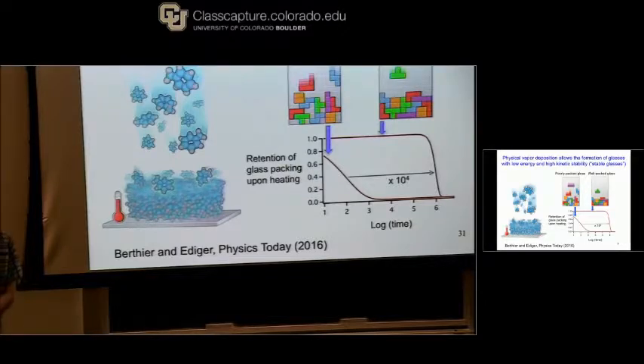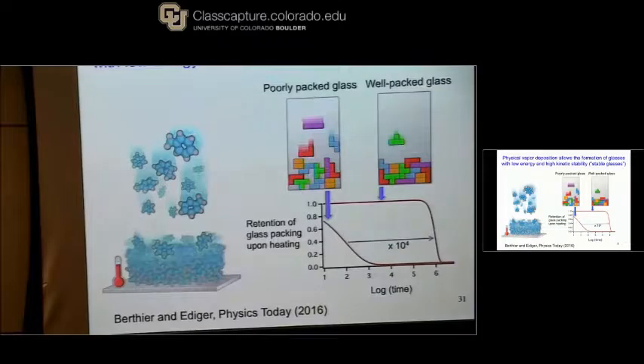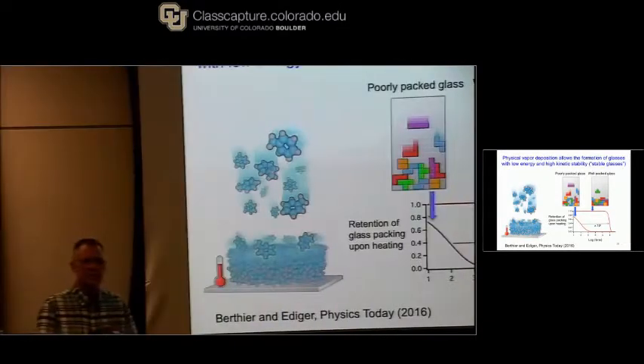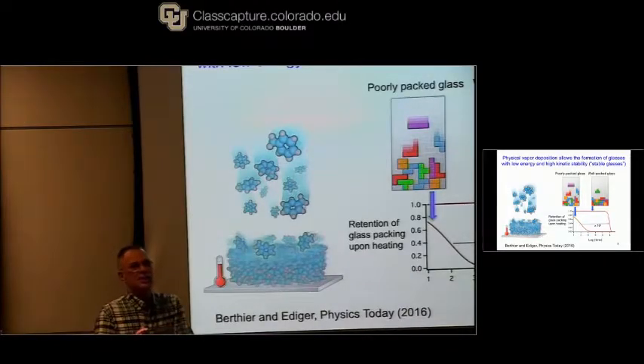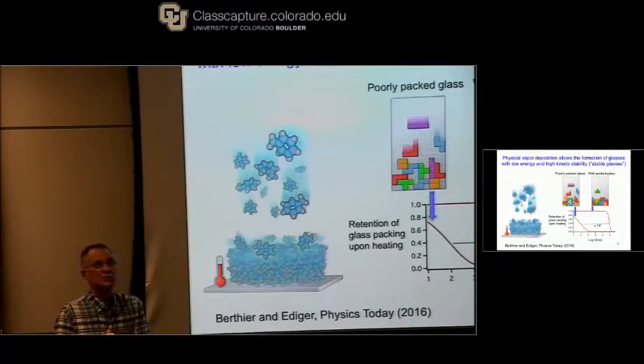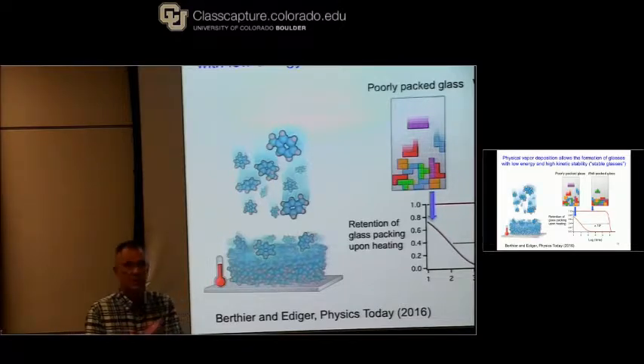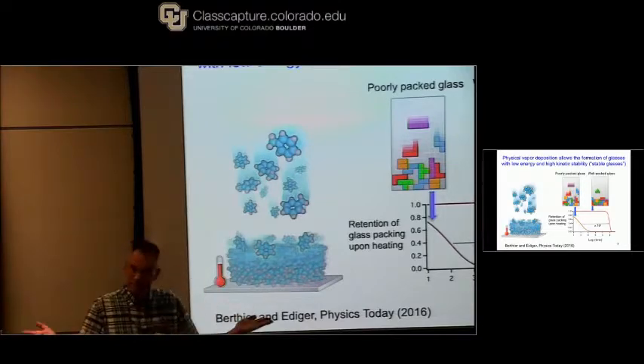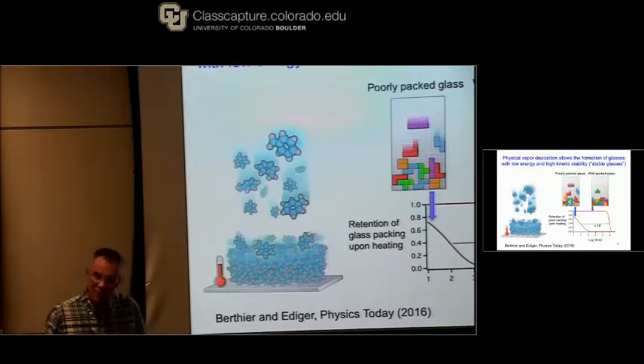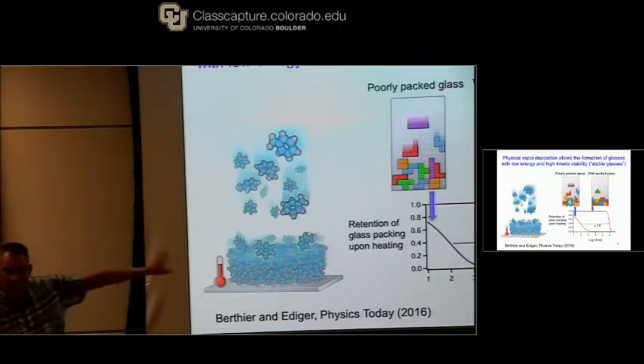Yes? How do you distinguish the defective crystal and the well-aged glass? Okay, I'll just give you a quick answer now, and later on. So if I were making a crystal, I would expect sharp diffraction patterns when I do X-ray, and I don't see them. The other thing is that when I heat these up, if I were making crystals, I would expect crystals to grow and take over the sample, and they don't. When I heat these things up, they're very kinetically stable, but when they finally fall apart, they fall apart into a liquid. So I think there's 2 good arguments that these are not crystalline materials.